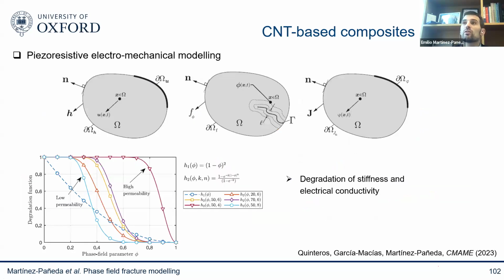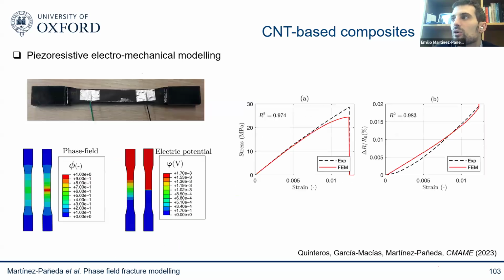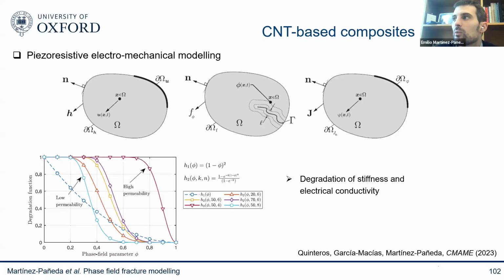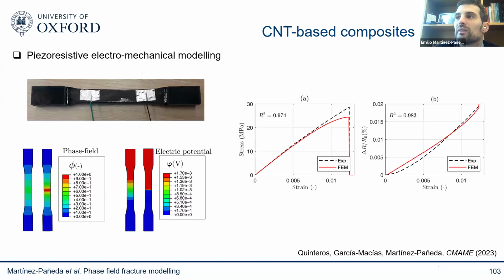And we have combined this with electromechanical modeling because we want to use those carbon nanotubes to tell us something about a structure. So we want to be able to capture what happens when cracks evolve in our structure, how we will be able to see this in terms of the electrical field. So we can come up with a multi-physics model where we degrade the stiffness and the electrical conductivity, and we can compare that to experiments.